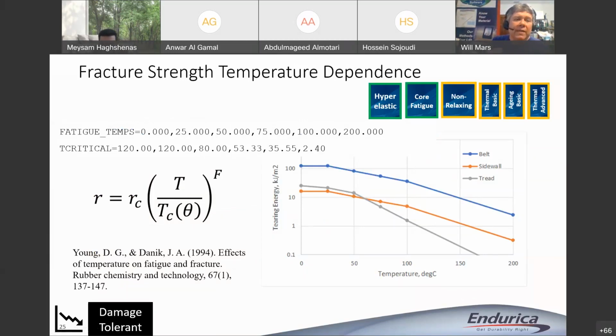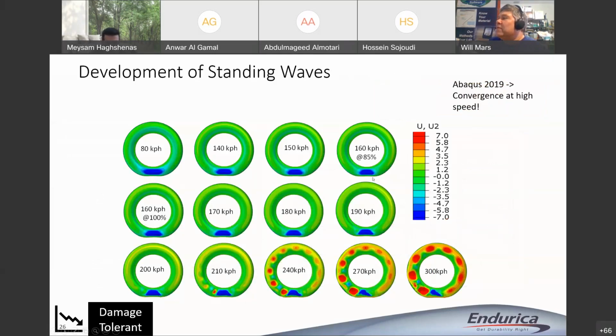We also need to model the temperature dependence of the crack growth rate law. This is a plot that shows the dependence of the strength of the rubber as a function of temperature. And this strength is one of the inputs to our crack growth rate law. So that lets us represent this thermal effect on the strength of the rubber in a tire. And now these are pictures of the tire model at different speeds, ranging from 80 kilometers an hour, right? There's one of these images for each of the steps in the schedule that I showed you earlier. And what you can see here is up to about 200 kilometers an hour, it's kind of boring. There's some modest changes in the solution.